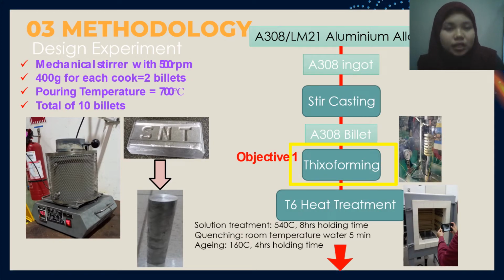For the design of experiment, I made a total of 10 billets by using stir casting. For every cook, 400 grams of ingot was used, and it must be heated until it reaches 700 degrees Celsius, which is above the melting point of the aluminium alloy, and then it is poured directly into the mold. After reaching 10 billets, I went on to the thixoforming process for my first objective, using 8 billets and leaving the other 2 billets for the S-cast samples. For the thixoforming process, the billet length needed was 11 cm to fit in the induction coil, and the compression temperature was 502 degrees Celsius. During this process, I had to avoid the elephant foot situation happening to my specimen.